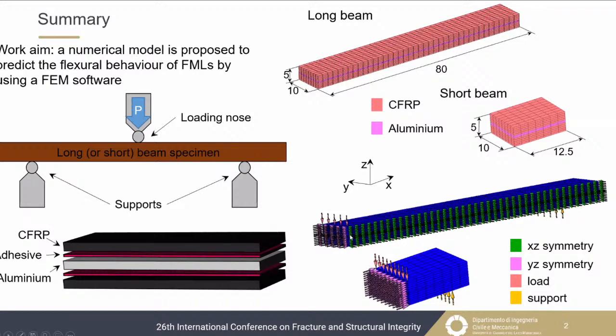As concerns the boundary conditions, we considered the plane of symmetry by blocking the normal displacement. The loading was simulated by applying a displacement at a constant speed, while the supports were simulated by impeding the vertical displacement of the nodes where the supports act.